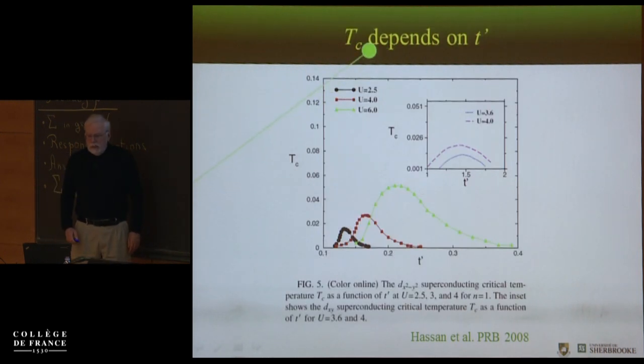Okay, now, so TC depends on T prime. So we are at a filling, and take a value of U. For example, U equals 6 is the green curve. And you see that the TC as a function of T prime has this dome shape. So there's an optimal frustration. That's the concept we want to introduce. So if you are too close to a filling, the pseudogap comes in and kills the superconductivity. If you're too far, there are not enough antiferromagnetic fluctuations.